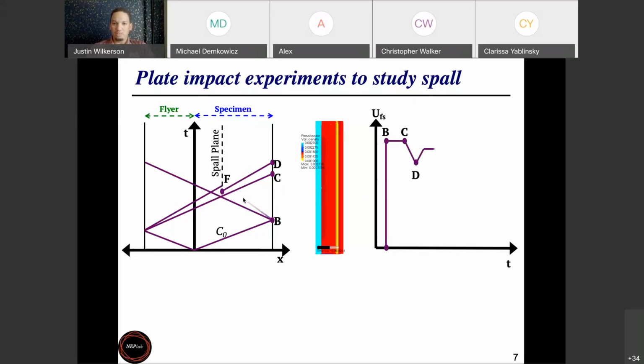So if I click through again, you can see in the simulation, I get the formation of this yellow region, which is a low density region, which is an indication that I've nucleated a bunch of voids or cracks or something like that, some kind of damage in the spall plane of the material. And then that's going to cause some implications over here in the free surface velocity history. Okay, so again, this is our main diagnostic measure here, free surface velocity versus time. So from that, we can back out a few things that tell us what was going on to the material before it failed and as it was failing.